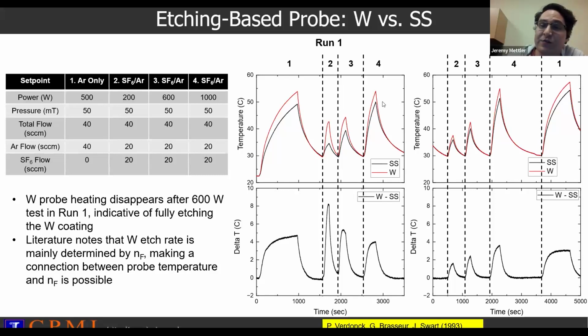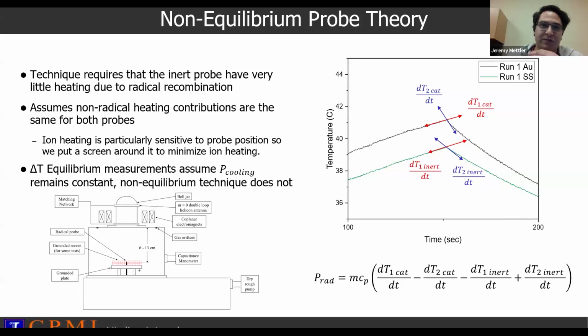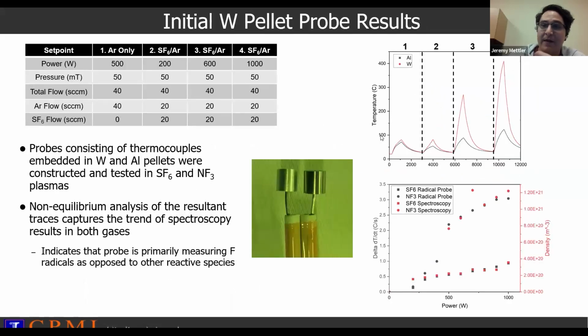And we see that temperature response actually decay, because we had a very thin coating of tungsten on our probes, and we managed to etch it completely clean in a matter of a few minutes. So, taking a step back to take an example of what the non-equilibrium measurement would look like, we take the slopes here, which is well suited to an etching probe. And then instead of just a thin coating of tungsten, we apply a large pellet of tungsten.